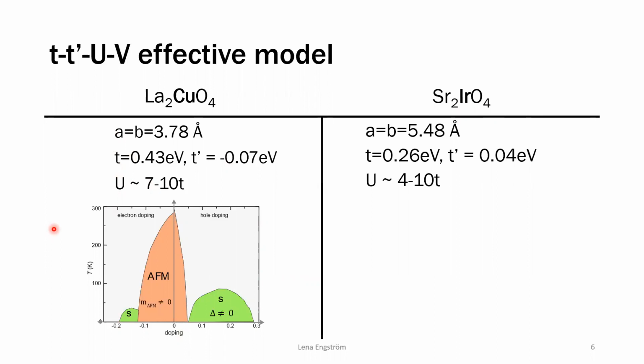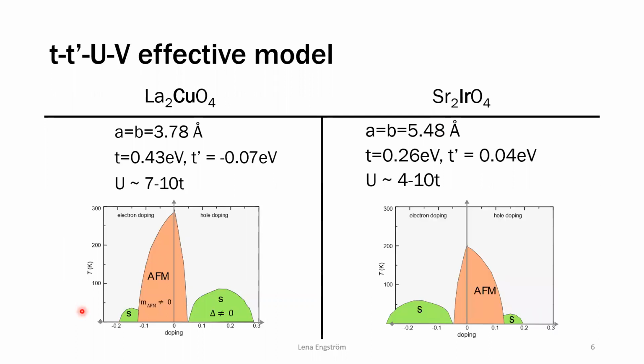Now, what you can see for the iridates is that there you actually have multiple bands, but if you just look at the ones closest to the Fermi surface, you can do the same fit, and you can basically see that all parameters are proportional to the cuprates, with one minus sign difference here. So the trick is then basically not to consider that they're different materials in a way, but just consider that it's the same model where you just plugged in different values that are just proportionally different.